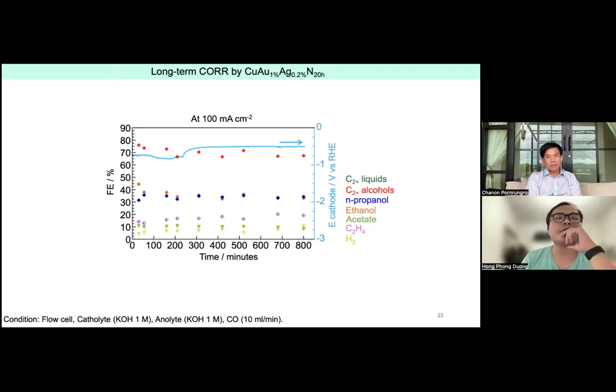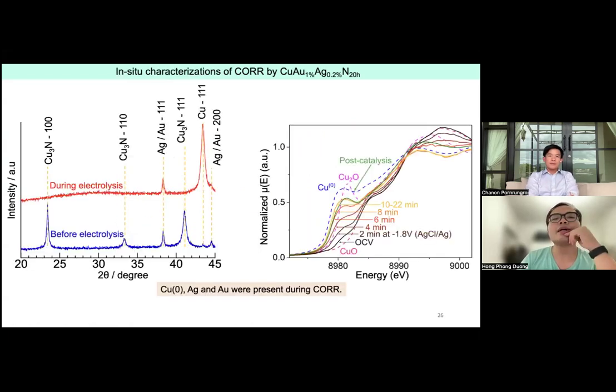Okay, and then we have to know how to characterize the material before and after electrolysis, and also we performed in situ characterization to know the status of our material. We are very lucky that we collaborated with Professor Jean-Marie Tarascon, who I think is one of the most famous experts in the field of battery research, at Collège de France. We collaborated with his group to perform the in situ XRD measurement, and we found that our sample during electrolysis contains metallic copper, silver, and gold. This result was also double checked and confirmed with the in situ XAS here as well.